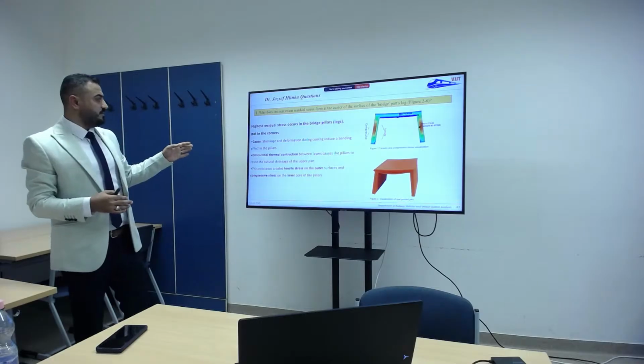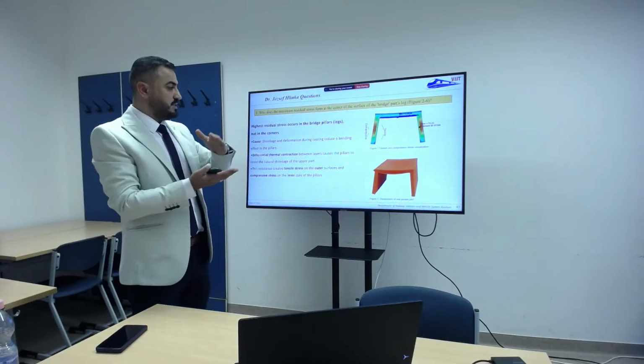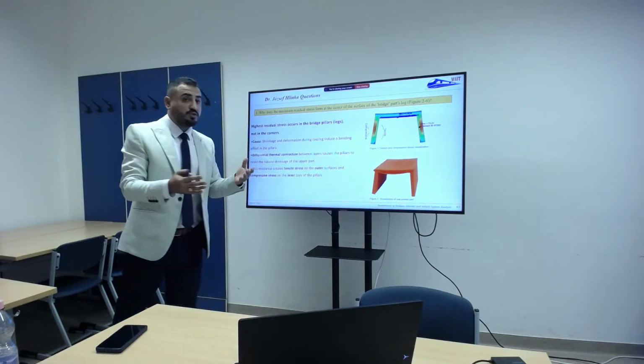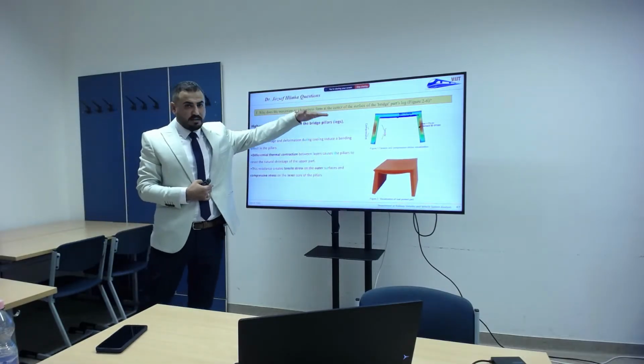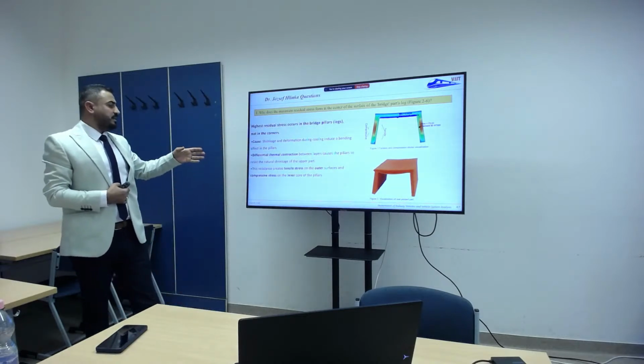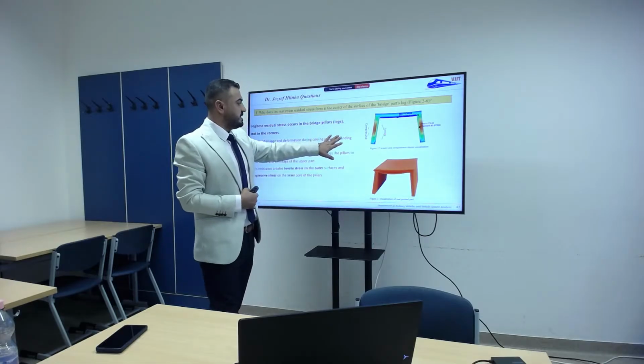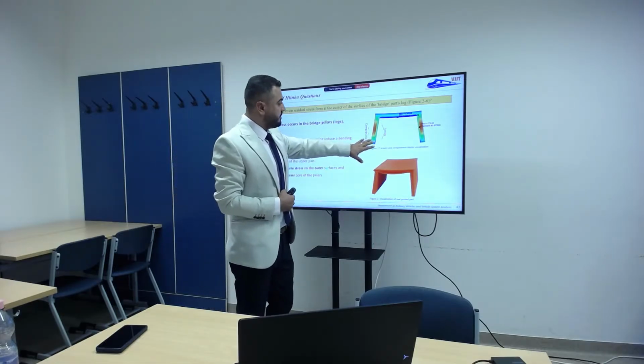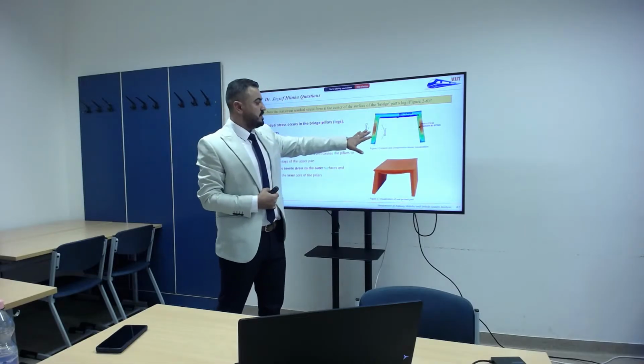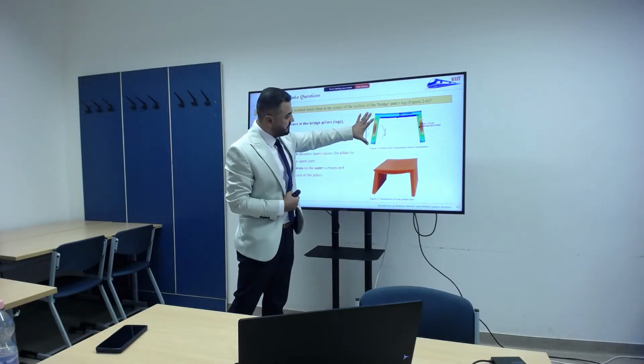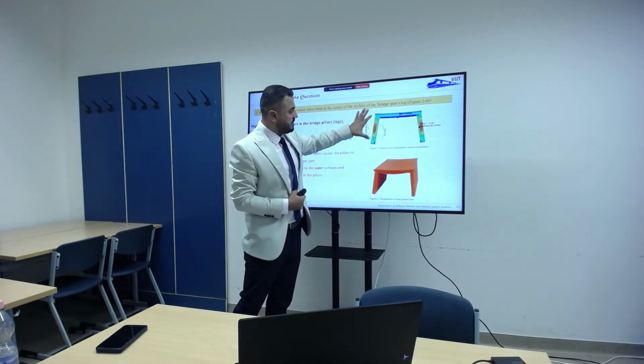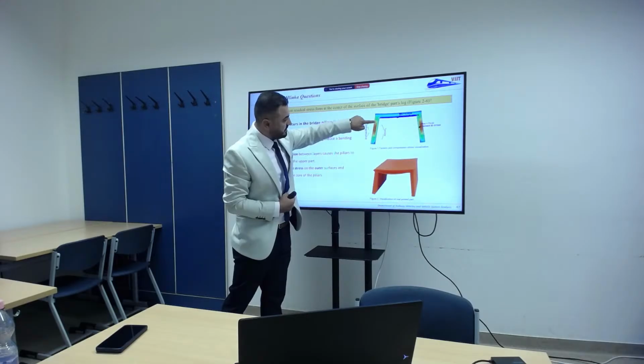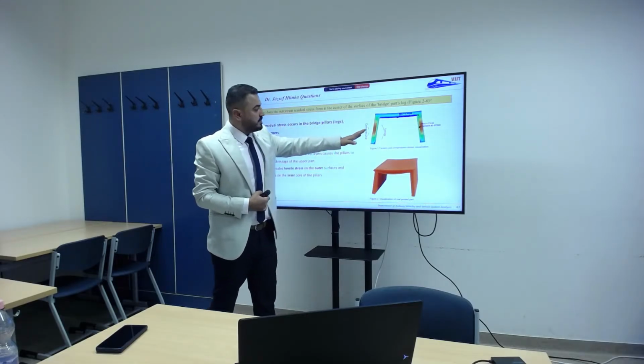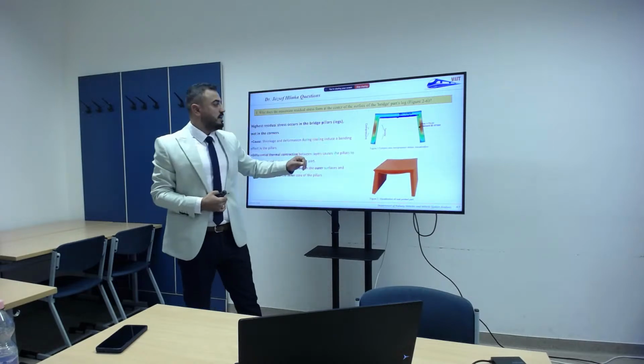Then there is a differential thermal contraction between layers, because printing layer upon layer caused the pillar to resist the natural shrinkage of the upper part when printing the top part of the bridge. This resistance creates tensile stress and compressive stress: the tensile on the outer surface and the compressive on the inner surface. I mean the outer surface of the leg itself, not the bridge, because the outer part will be less. If you take the leg as an independent part, you can see the line here, which is the cause of the bending stress, the compressive from inside and the tensile from the outer surface.